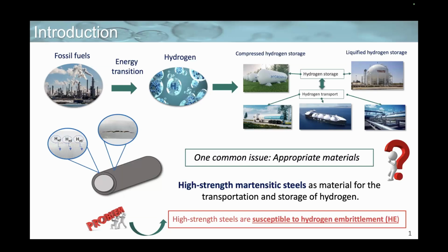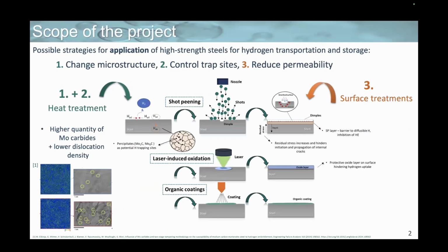One of the possible materials which could be used are the high-strength martensitic steels. Nevertheless, it is well known that these steels are highly susceptible to the phenomenon of hydrogen embrittlement, which imposes obstacles in their practical application in the hydrogen sector. To overcome these obstacles, several actions can be undertaken. In the course of my PhD thesis, we tried to change the microstructure of the steel, control the trap sites, and reduce the permeability.